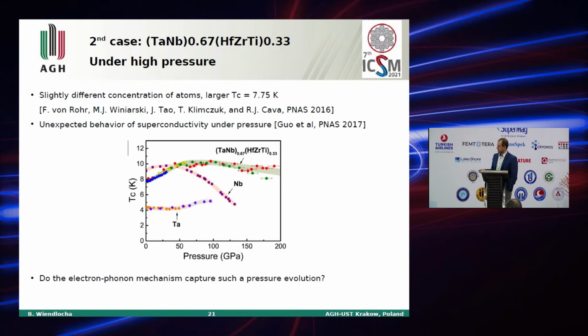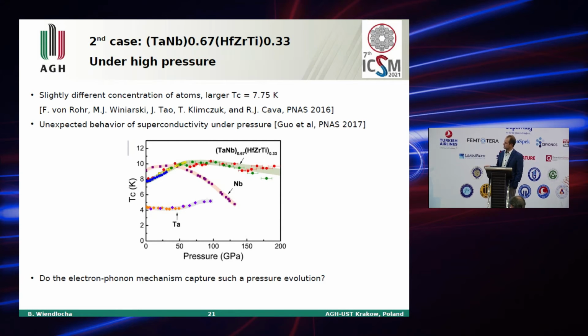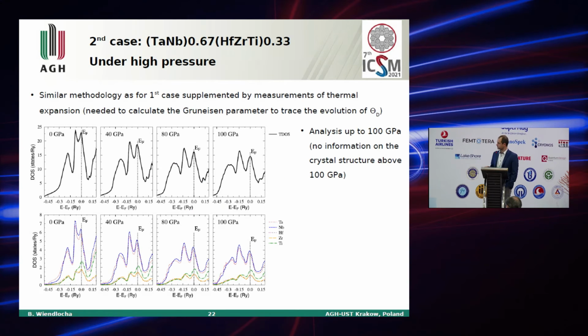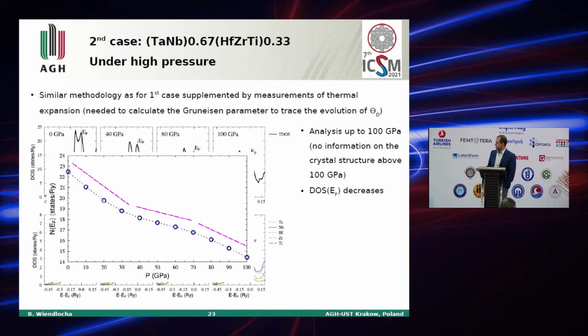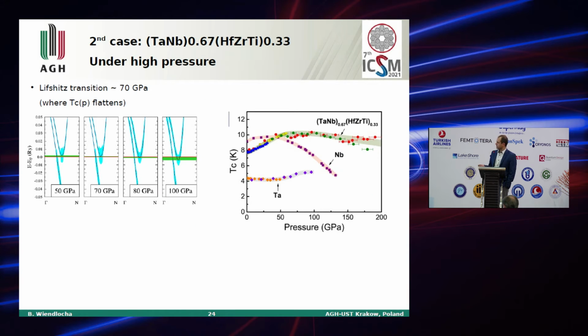So it was tested up to 200 GPa, and the critical temperature increases, and around 70 GPa it stabilizes and stays at the enhanced level of 10 Kelvin. So we are interested in whether we are also able to explain this pressure evolution of TC using this rather simplified treatment. So here is the electronic structure, density of states of this material. Total DOS decreases with pressure, as you can see here. We observe the Lifshitz transition around 70 GPa, so this band starts to contribute to the Fermi surface at higher pressure, which was not the case at the lower pressure. This is near the pressure where the TC curve stabilizes.